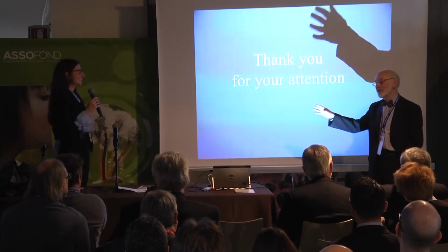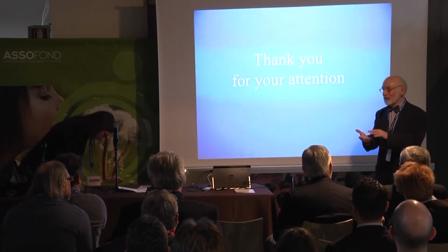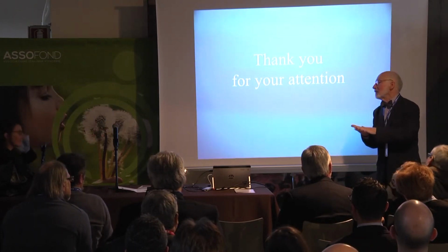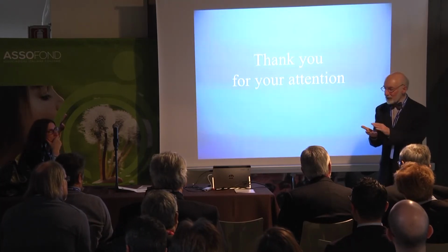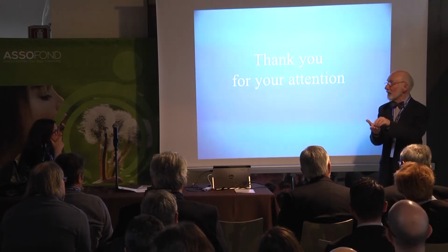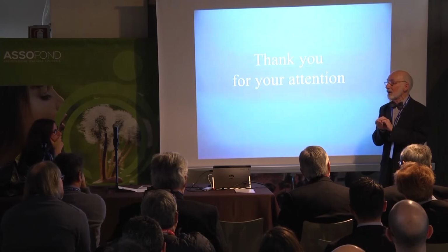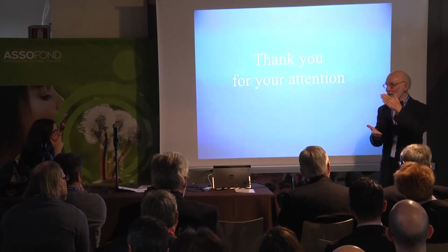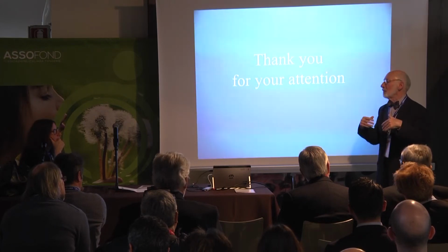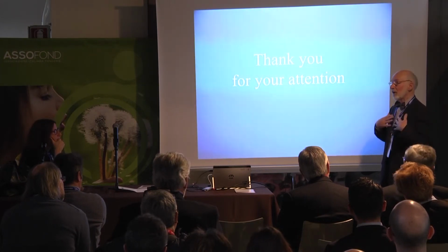These are wonderful questions, thank you. Normally, when you cut your casting, polish it and look at it under the microscope, it's not possible to see the bifilms. However, what you can see very often are inclusions sitting at some grain boundaries, and those are the grain boundaries which have a bifilm in them. Because what I think is, inclusions don't precipitate at grain boundaries. They only precipitate on bifilms. They always sit on the outside.